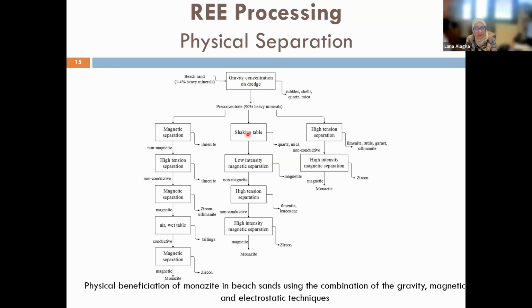It depends on what you have in your material. Sometimes low intensity magnetic separation is used if you have magnetite, for example. Magnetite is a ferromagnetic material that can be concentrated using a low intensity magnetic separator. If you have hematite, you need to use a high intensity magnetic separator, or other magnetic material such as ilmenite. They are paramagnetic materials.